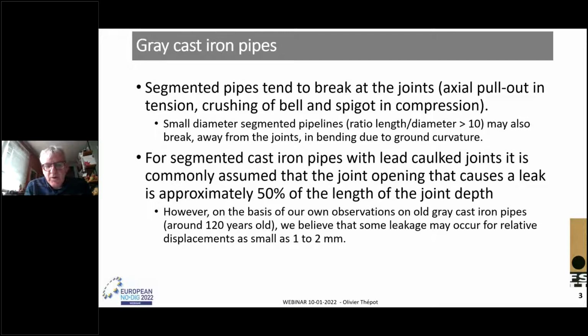Segmented pipes tend to break at the joints. Small diameter segmented pipelines with a length-to-diameter ratio higher than 10 may also break away from the joints in bending due to ground curvature. For segmented cast iron pipes with lead-caulked joints, it is commonly assumed that the joint opening that causes a leak is approximately 50% of the joint depth. However, on the basis of our own observation on old grey cast iron pipes, around 120 years old, we believe that some leakage may occur for relative displacement as small as 1 to 2 millimeters.